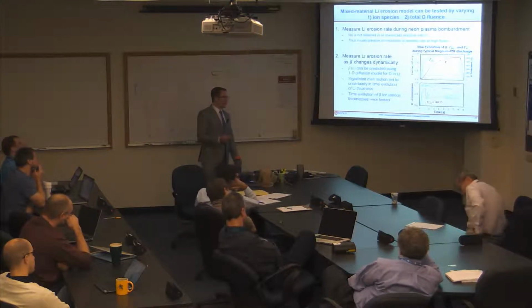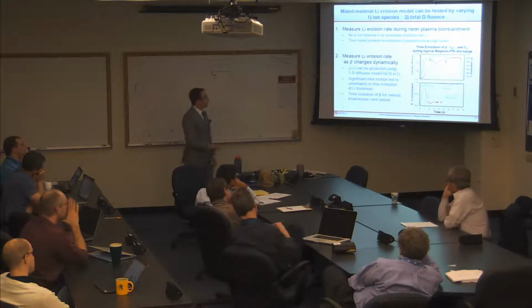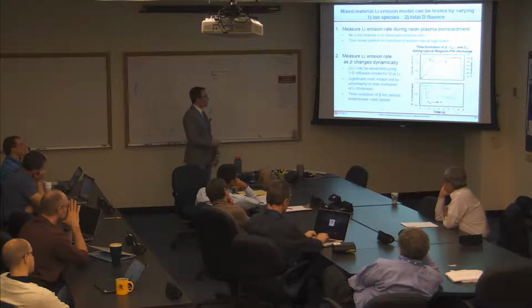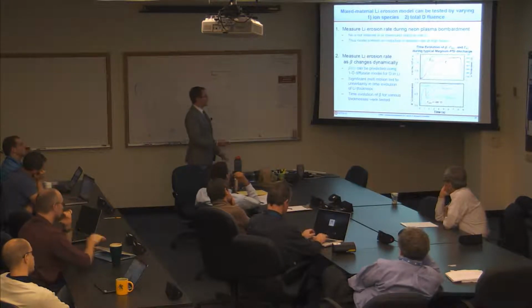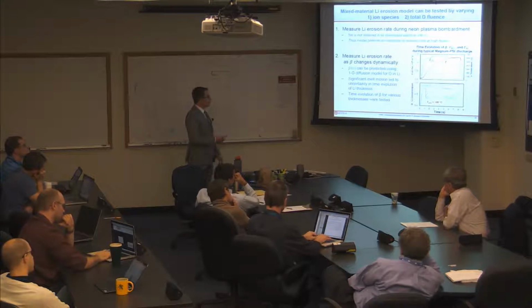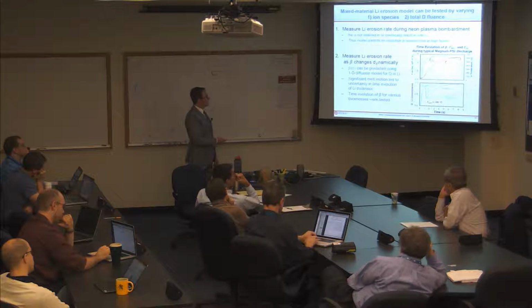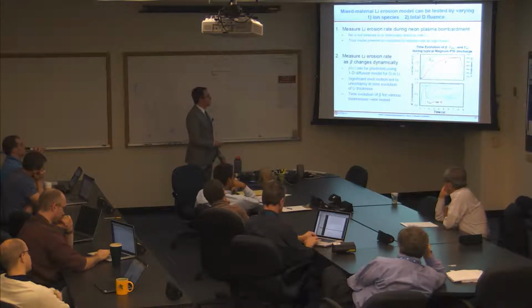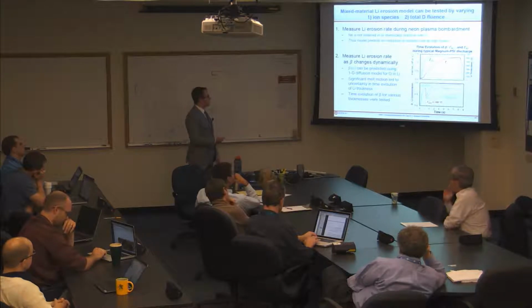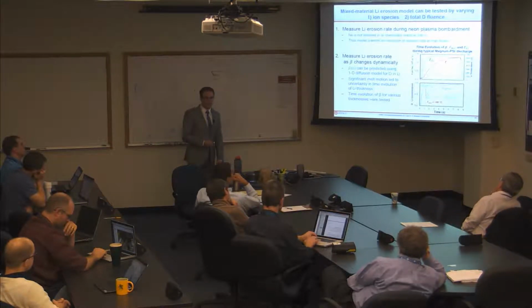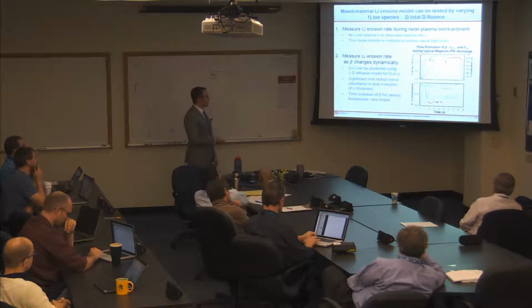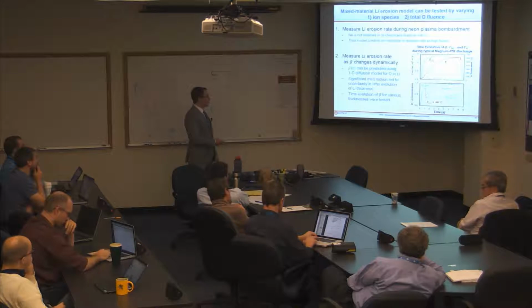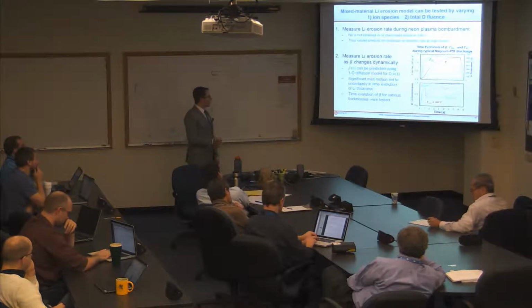So if you have some thickness of lithium layer and you have some bombardment rate, what is the predicted deuterium to lithium concentration? Well, I talked about that a little bit already, but we can actually do some more specific modeling here. So first off, if you don't use deuterium, if you use, say, neon instead, then you don't expect any deuterium formation. So that's sort of the control experiment, that you don't expect any reduction in the erosion rate. And then you measure the erosion rate as a function of beta, the deuterium to lithium concentration. And I can predict what the deuterium to lithium concentrations will be using my model.